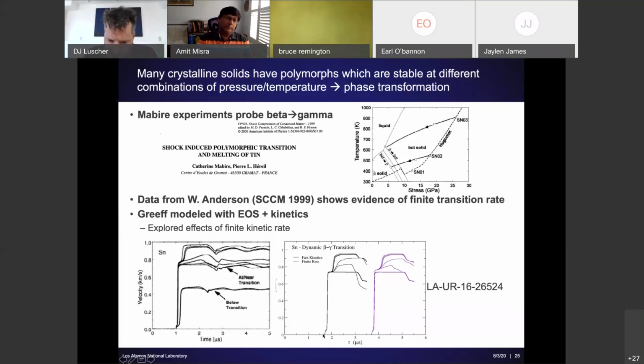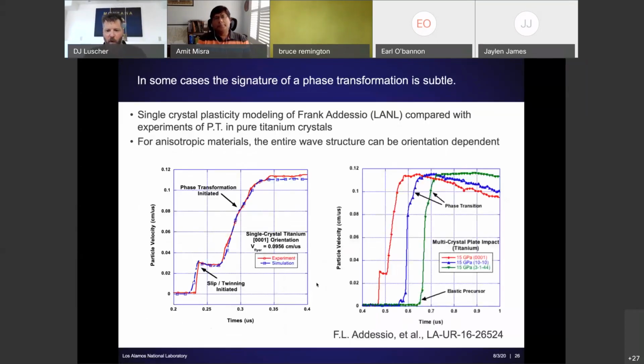So to connect it back with earlier in the lecture, we see a bit of an elastic precursor here, then a jump, and then depending on how hard we've hit the material, we're seeing an arrival of another wave that transitions into the gamma phase, from the beta phase into the gamma phase. And the shapes of those profiles are being affected by the assumption of the kinetics of that transformation.